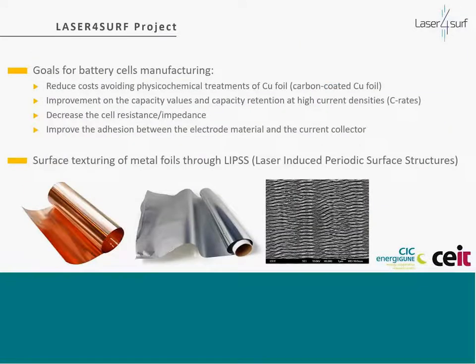So what are the goals for this application field in this project? Mainly to reduce the cost of the cells, avoiding chemical treatments of the copper foil. We try to remove the carbon-coated copper foil and replace it with just a laser-treated copper foil. In this way, we can remove one of the treatments and also the chemicals associated with this coating process. We also think that this process can improve the capacity values and the capacity retention at high current densities, and can also decrease the cell resistance and impedance. Additionally, by structuring the current collectors, we can improve the adhesion between the electrode material and the current collector, so maybe another process can be removed, or we can improve this adhesion.